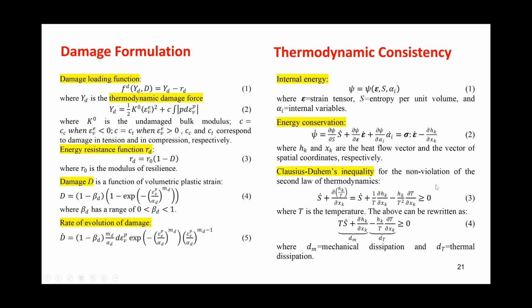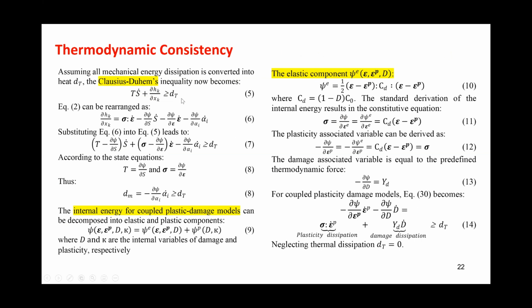We apply the Clausius-Duhem inequality for the non-violation of the second law of thermodynamics. So the rate of the entropy should be equal to the rate of the ratio of the heat flow and the temperature, as a derivative of the coordinates. We can simplify this and it comes up to this. And the sum of all these components should be positive or equal to 0 to be consistent with the second law of thermodynamics. Okay, so we can split the above into the mechanical dissipation, that's the stress and strain dissipation, and the thermal dissipation. Okay, again, this is the Clausius-Duhem equation, and I'm not going to go through that.